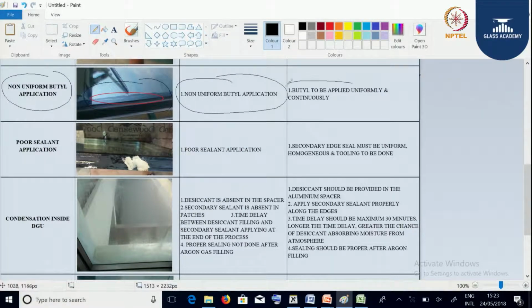Next defect we are going to get in the DGU is poor sealant application. You can see there is insufficient depth or missing continuity in the sealant. This is because of poor sealant application. We can overcome this issue by maintaining a proper edge seal, ensuring uniformity, and tooling the sealant once the pasting is done.